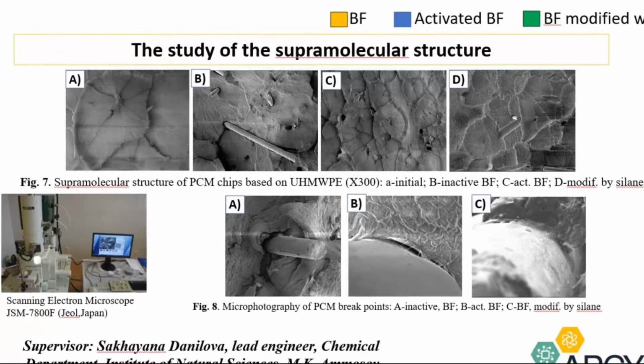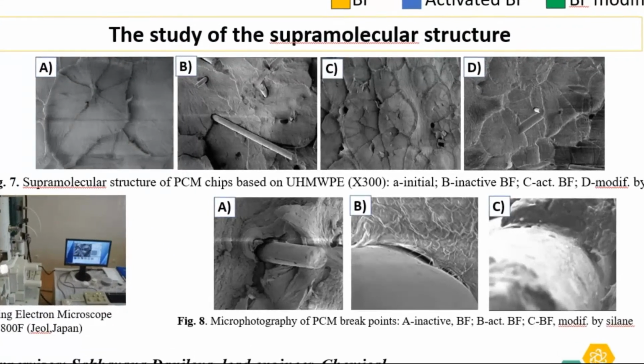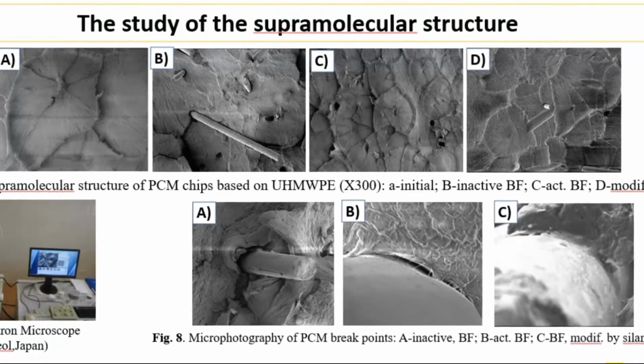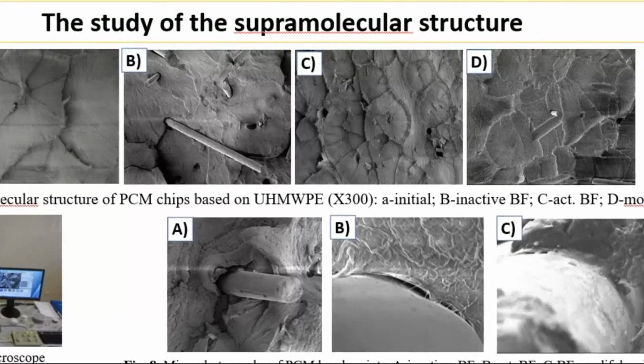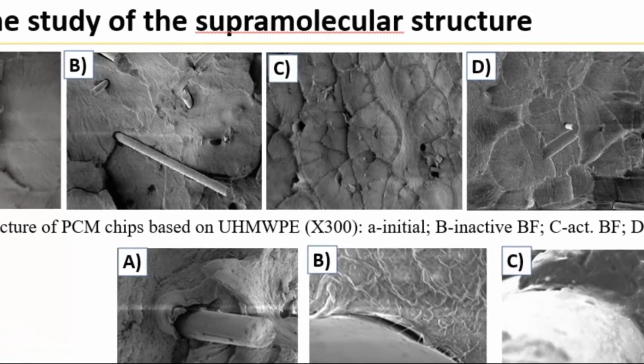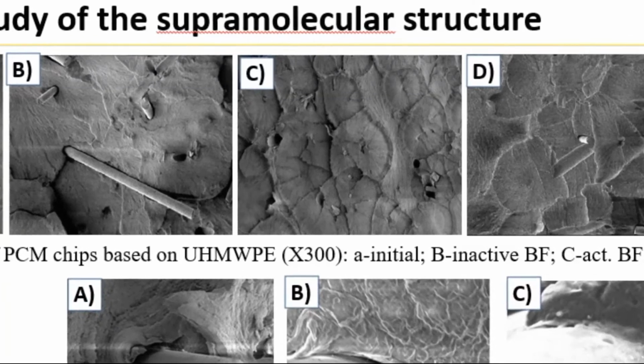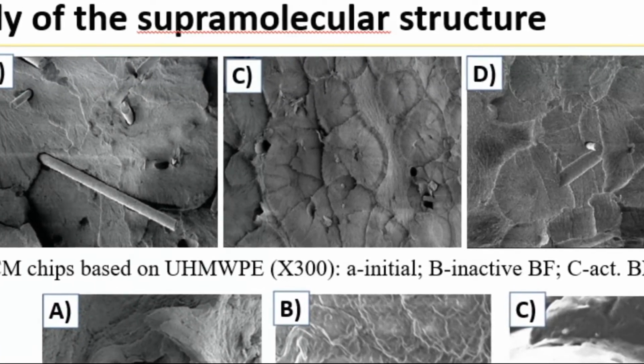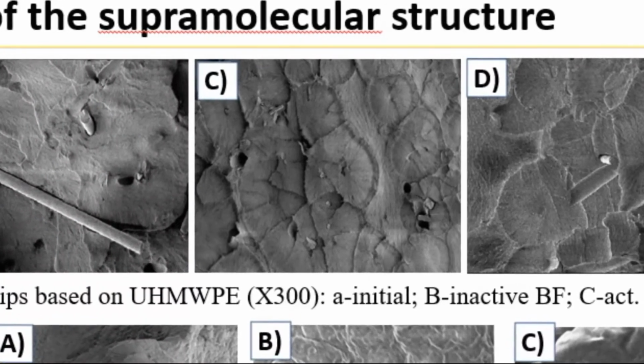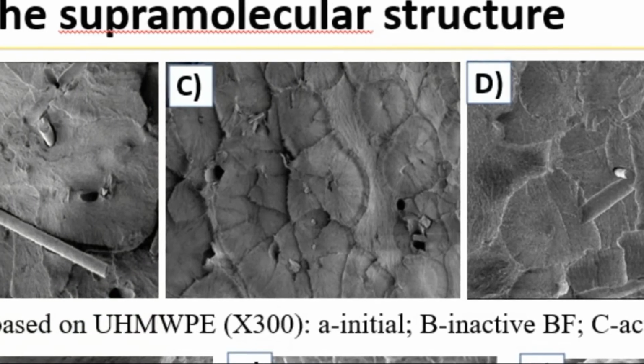In this figure, one can see that the composite materials containing mechanically modified natural basalt fibers show substantial fiber grinding. These short fibers exhibit all the characteristics of a dispersed filler during crystallization, being a center of crystallization. Therefore, these short fibers contribute to the formation of spherulites with small structure elements.